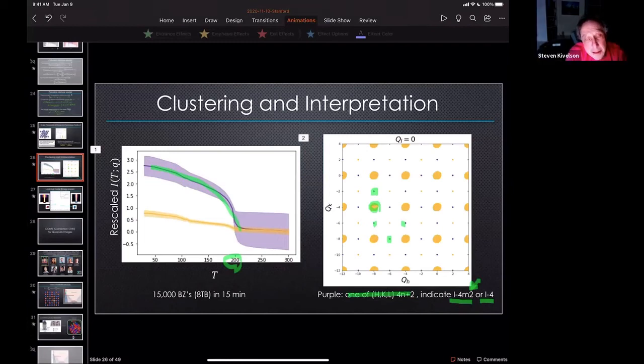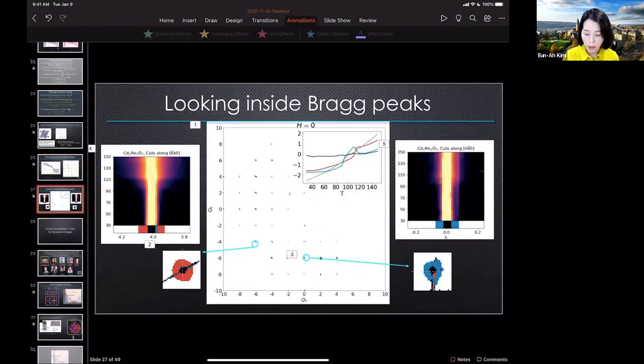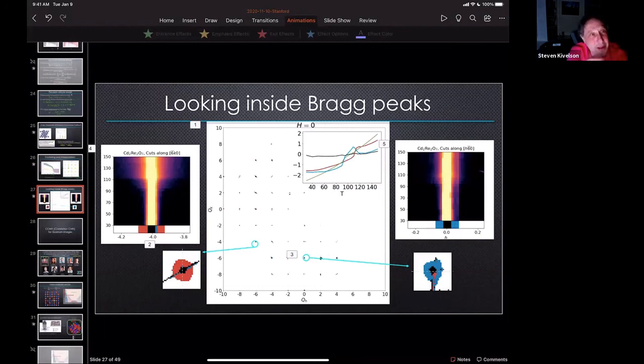Right. So it's looking at the pattern of the diffuse scattering, which is telling us about the fluctuations. Right, the pattern and the temperature dependence. When I said this is diffuse scattering, my colleagues again didn't believe me. They said, no, you don't have diffuse scattering over a whole phase. You can have diffuse scattering near a critical point, but you wouldn't have this wide diffuse scattering over a whole phase. And indeed, it was an unusual thing. The reason we had diffuse scattering over a whole phase, this phase two, was because it was a Goldstone mode. That I don't completely understand either. I understand it's a two-dimensional representation, but still, mm-hmm.